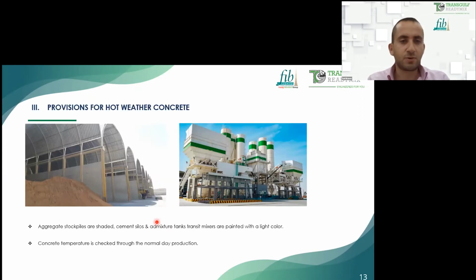We continue on the inspection procedure. Provisions for hot weather concrete. I mentioned this one because it's important to control the temperature of the concrete, since the United Arab Emirates temperature during the summer reaches more than 45 degrees Celsius. So a lot of energy is consumed to cool down the temperature of the concrete. We use flake ice, we use chilled water. The shades are covered, and the colors used for the transit mixers and cement silos must be light to make a difference. So this is part of the audit procedure as well.